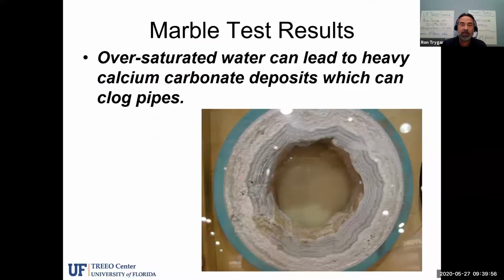And then we're going to go through the motions of adding the lime slurry or the calcium carbonate to the bottle and mix it up. So we have initial sample results before we did this, and now we're going to come up with an after effect. So again, we're going to filter out some of that water, and we're going to run the tests again. So the results, what this means to us, is that if the water was already full or saturated with calcium carbonate in the beginning, and we tried to force more calcium carbonate into the solution in that stoppered bottle, the calcium carbonate tends to come out of solution even more so than what we put in there. So the results actually show a reduction in the calcium hardness and the alkalinity of that water sample after we've done all this calcium addition.